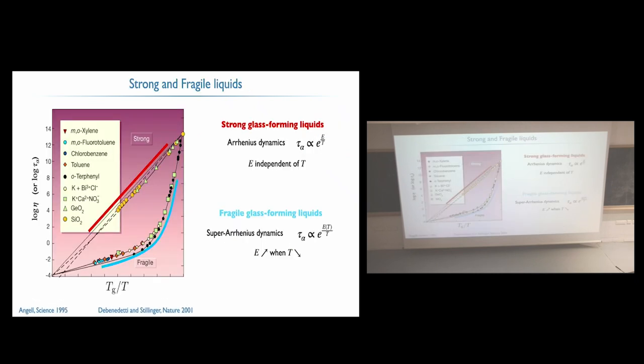So that's quite spectacular. So we wanted to explain a little bit more this question of Arrhenius or not. And actually, all glasses are not, let's say, equally interesting or challenging. There are glasses that are called strong and others that are called fragile. So again, in this Arrhenius plot, for these strong glass-forming liquids, if you look at the relaxation time, so the time typically for a molecule to rearrange, it really follows an Arrhenius law with an energy barrier that doesn't depend on temperature. It means that, okay, the liquid slows down, but it's something that's really well understood. It's simply that you have an energy barrier to overcome, and you get Arrhenius, and that's completely fine.